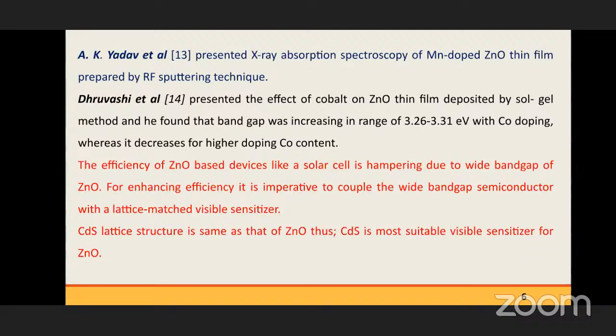the band gap increased in the range of 3.26 to 3.31 electron volt as Co doping increased, and it decreased for higher Co doping content. The efficiency of ZnO based devices like solar cells is hampered due to the wide band gap of ZnO. For enhancing the efficiency, it is imperative to couple the wide band gap semiconductor with a lattice matched visible sensitizer. CdS lattice structure is the same as ZnO. Thus, CdS is the most suitable visible sensitizer for ZnO.